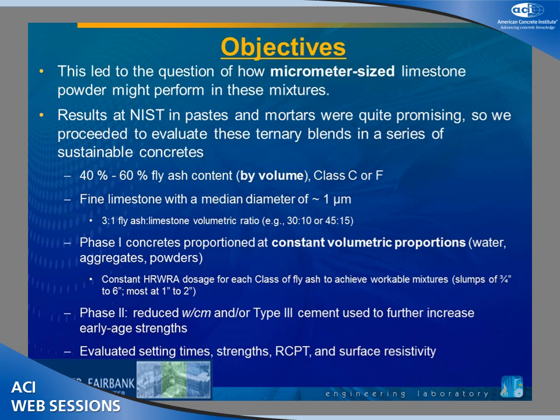The Class C fly ash is a very contrary C ash. It's very reactive. It will flash set with just water, but it won't really develop strength beyond that. It'll liberate a lot of heat and flash set. And then if you put it in a cement system, it'll retard the hydration 8-10 hours. So it's very problematic. It's a very interesting material to try to work with. It has about 25% calcium oxide.